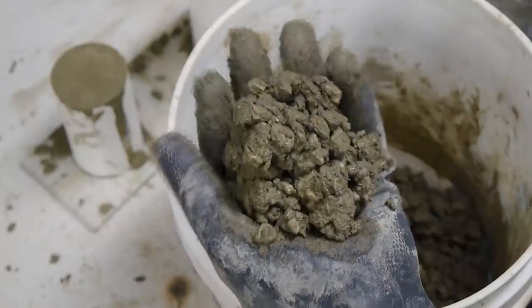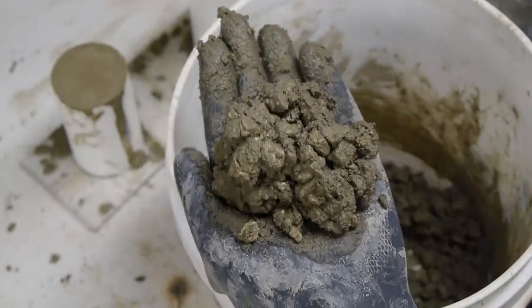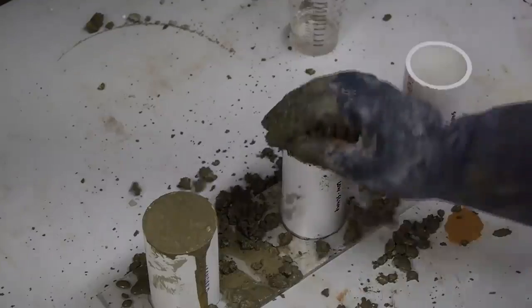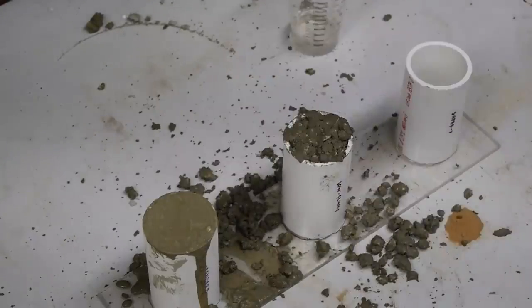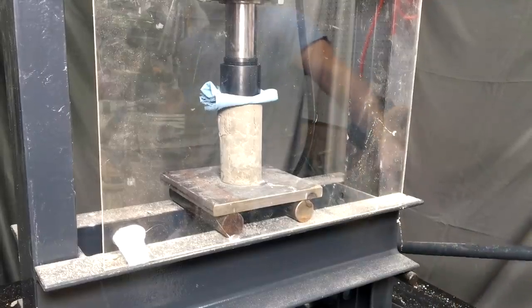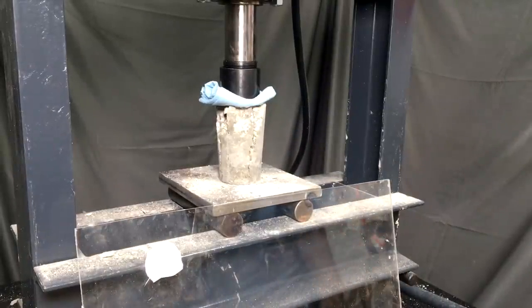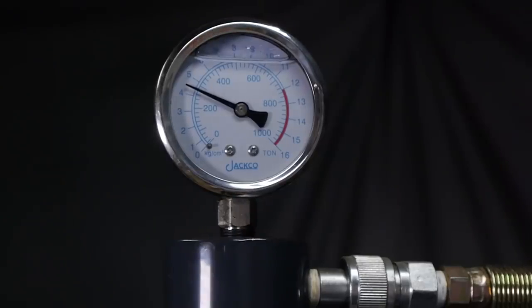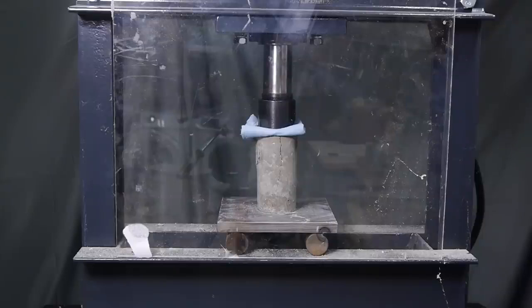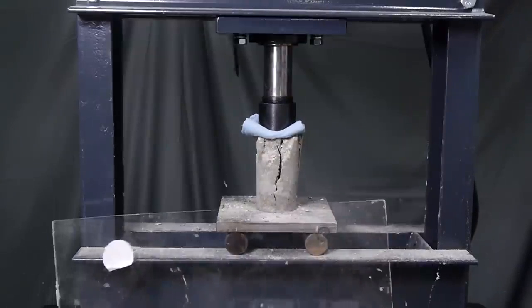For the next batch, I added a lot less water. You can see that the mix is much less workable. It doesn't flow at all. It takes a lot of work to compact it into the mold. However, after a week of curing, the sample is much stronger than the first mix. It didn't break until I almost maxed out my press at 3000 psi, or 21 megapascals.